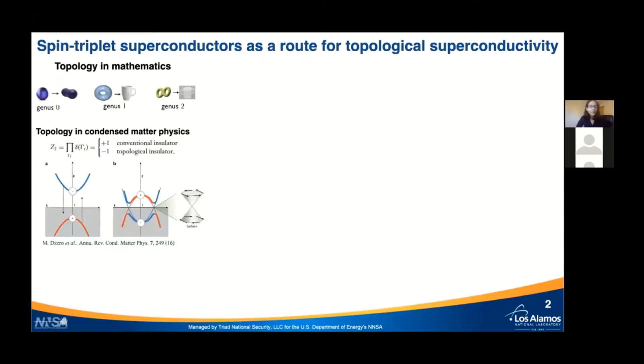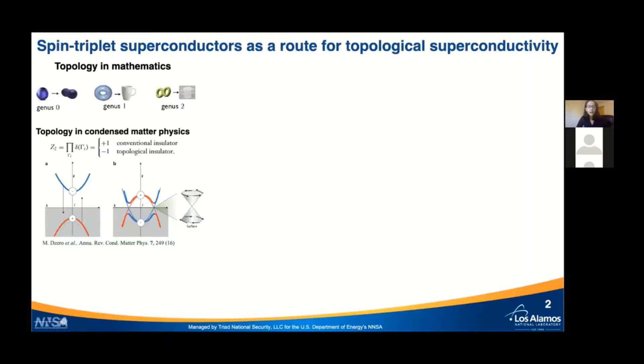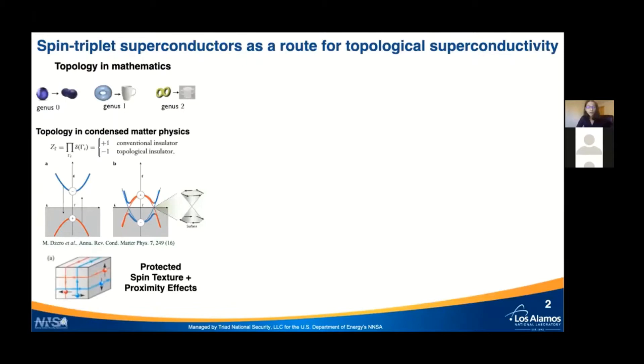More recently, this concept was extended to condensed matter physics. We need to look at the band structure and calculate the topological invariant. For a simple system with inversion symmetry and no time reversal symmetry breaking, we can calculate the so-called Z2 index, which is just a product of the parity at the high symmetry points of the Brillouin zone. A trivial band structure vs. the one that leads to a topological insulating state has protected spin textures on its surface, and possibly proximity effects when near an S-wave superconductor. People have been searching for Majorana fermions that may exist at this interface — these exotic particles are their own antiparticles and are argued to be candidates for quantum qubits.